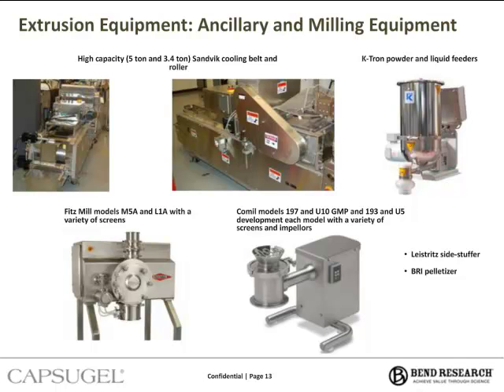We also have several K-Tron loss-in-weight feeders, and several of these can be used during development to fast prototype formulations if the powders are not blended and fed in independently to the extruder. We also have some high pressure ISCO syringe pumps for liquid injection, and we have a variety of mills and milling equipment. What can be seen at the bottom of the slide is our Fitz mill, and we have an M5A and an L1A, and we have a variety of co-mills used in development and GMP.